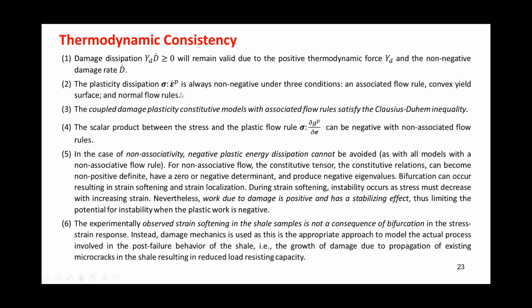Okay, those are the three. However, as assumed in the model, it is non-associative, so we already violate this. So we have a non-associative flow rule. This product of the stress tensor and the gradient of the plastic potential can be negative. In this case, we cannot avoid negative dissipation.